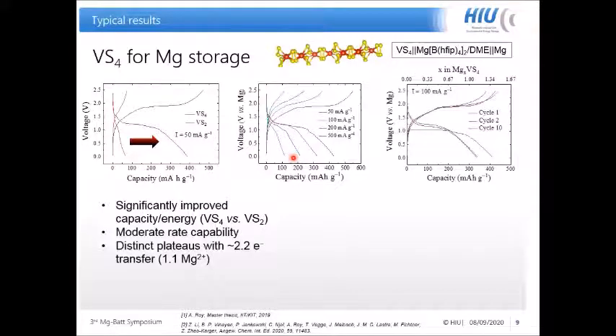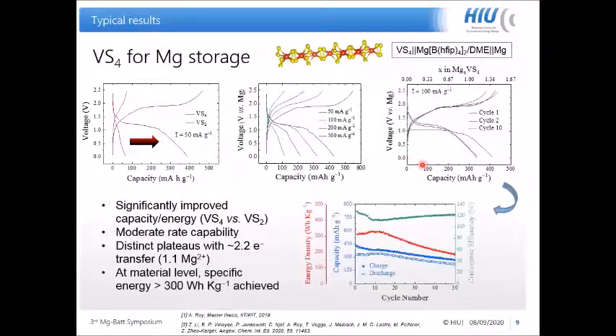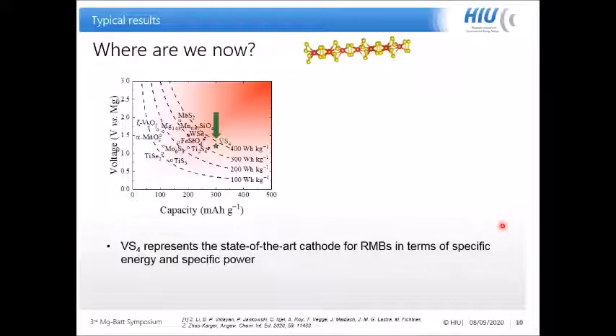In the cycling performance, we see the charge-discharge curves almost overlap after the initial cycle, and this indicates good reversibility. The cell could deliver a discharge capacity of around 350 milliampere-hours per gram, which corresponds to 1.1 magnesium or 2.2 electron transfer. With this high capacity and the nice plateaus, we could reach a specific energy of 300 watt-hours per kilogram at the material level. We also compared the capacity and voltage of our VS4 cathode with other reported cathodes, and from this figure we see that VS4 already represents the state-of-the-art cathode for magnesium batteries in terms of both specific energy and specific power.